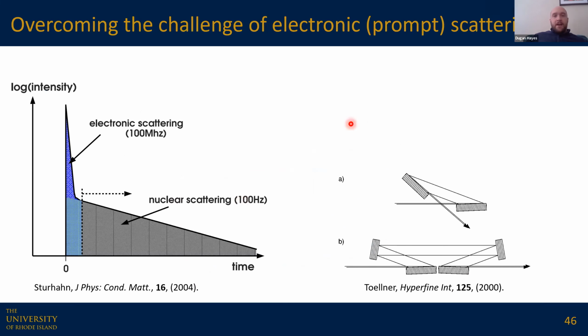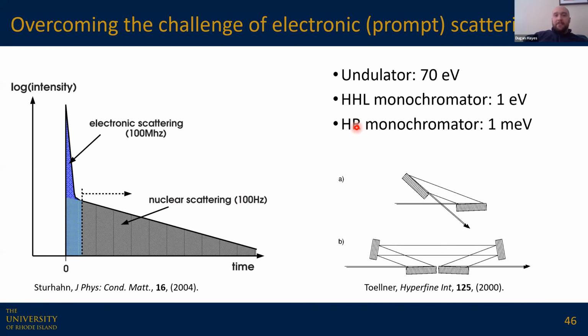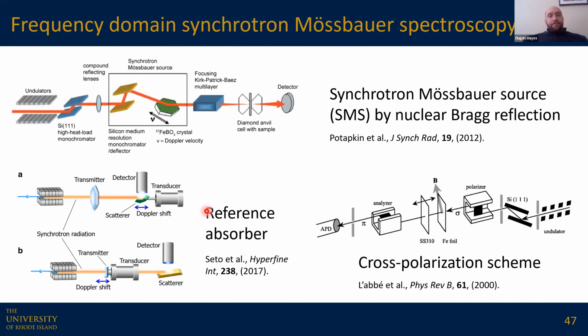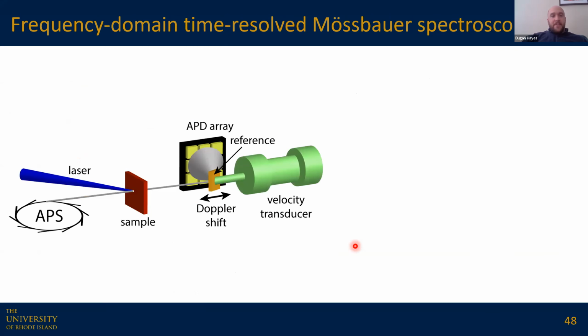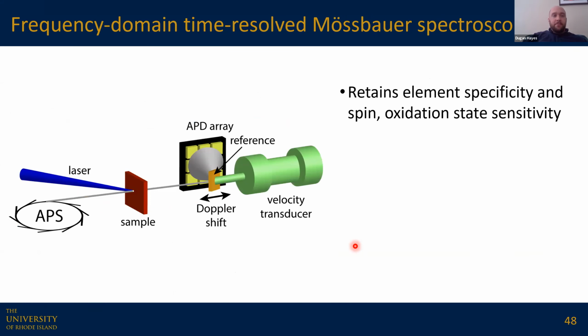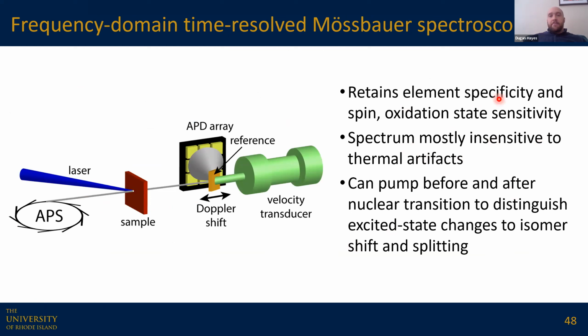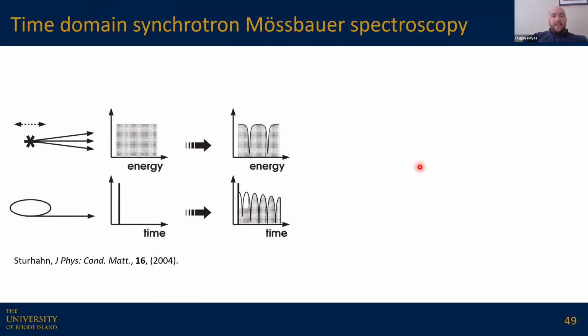One of the big challenges in this approach is that we can have these high resolution monochromators at a nuclear resonance beamline that get us 1 milli eV bandwidth, but that's still much broader than our nuclear resonance. And so our temporal response, if we're doing this in the time domain, is often swamped out by prompt electronic scattering. So there are frequency domain approaches around this. We thought we could combine a frequency domain approach with laser excitation to get all the benefits of transient X-ray spectroscopy, but hopefully be mostly insensitive to thermal artifacts.